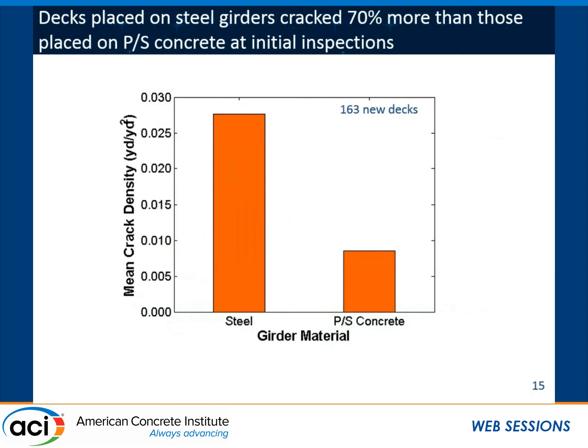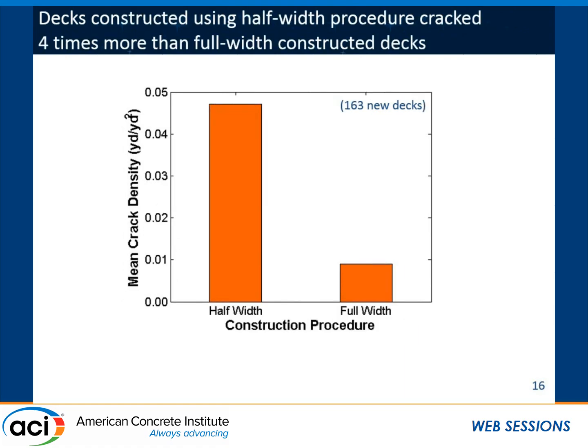We also looked at the 163 decks. About a third of them were placed on steel girders and the other ones on concrete girders. We found that there seems to be a significant difference between the cracking density of the two. We did not explore the cause of this much further. It could be due to the stiffness of steel. It could be due to temperature development in concrete and how much of this is sinked into steel, and so on. But it looks like, just based on field data, that pre-stressed concrete girders are doing better.